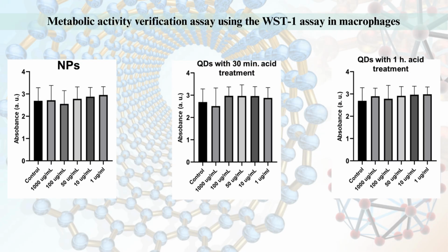On the other hand, the results of the WST-1 assay showed no significant differences between the conditions evaluated with the different materials, compared to the negative control. These results suggest that, under the experimental conditions used, none of the nanomaterials evaluated significantly affected cellular metabolism, which reinforces their potential biocompatibility.